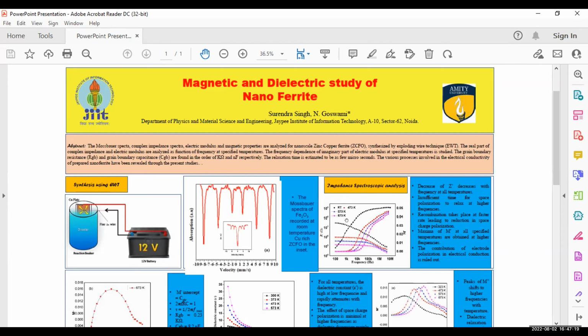Recombination takes place at a faster rate, leading to a reduction in the space charge polarization. We can see the maximum of M, the electrical modulus, at all specified temperatures is obtained at higher temperatures. The contribution of electrode polarization in electrical conduction is ruled out. We have taken one temperature particularly so that the modulus intercept gives the grain boundary capacitance, and with the help of the peak we could find the frequency and the relaxation time. The resistance of the grain boundary was calculated to be 0.03 kilo ohms, the capacitance of the grain boundary was found to be 8.2 nanofarad, and the relaxation time was calculated to be 1.9 microsecond.